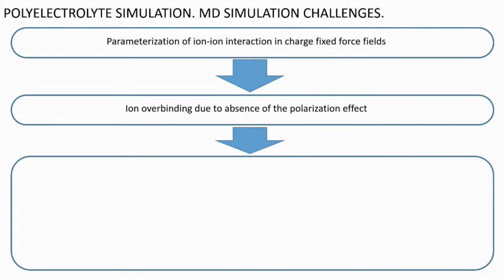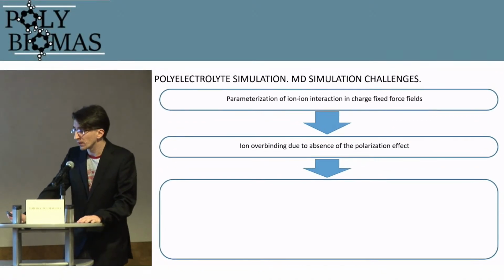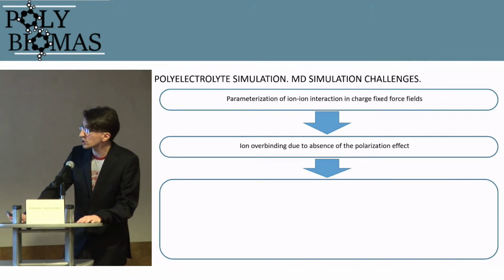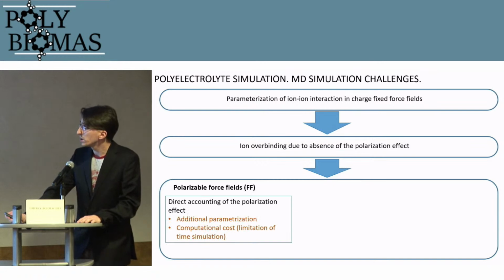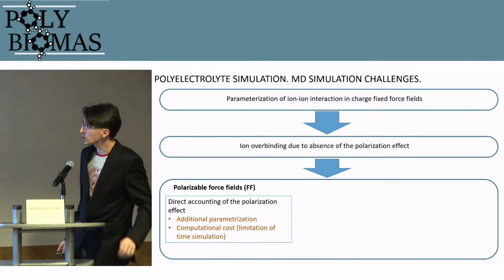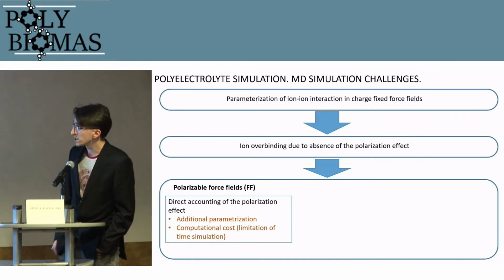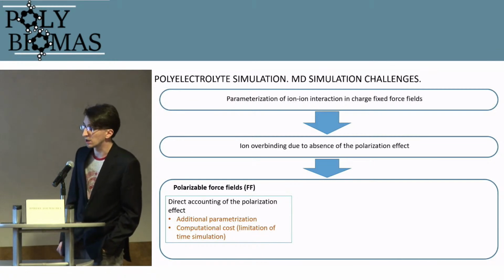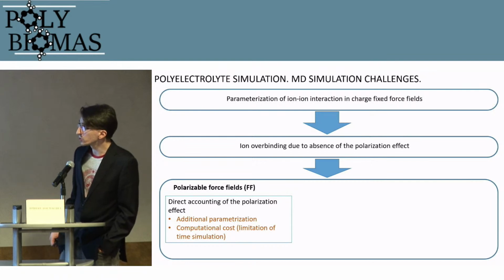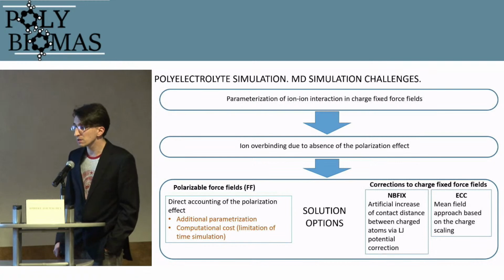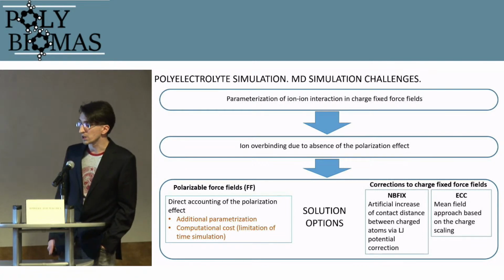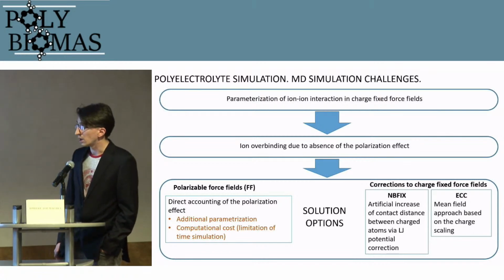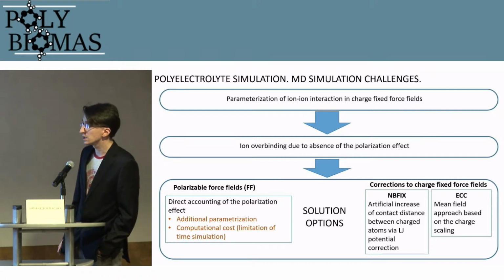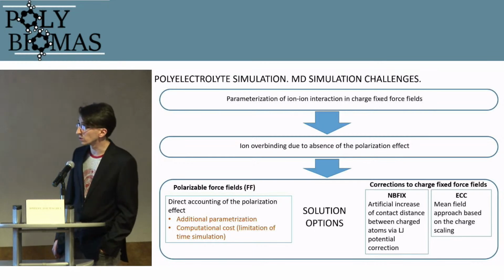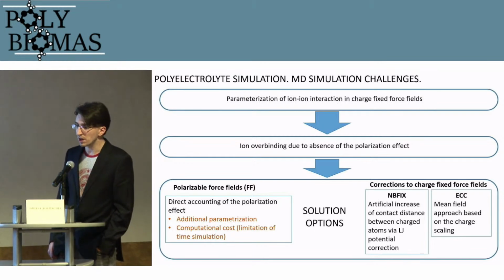And when we talk about molecular dynamics simulation of polyelectrolytes, it is important to know the challenges that we face. The first challenge was well described by Gekter yesterday, but I want to talk about it a little bit more. The parameterization of ion-ion interaction in charge-fixed force fields, and the absence of polarization effects, causes ion overbinding on polyelectrolyte. To solve this problem, one can use, of course, polarizable force fields with direct account of polarization effect, but it has a very high computational cost, and this high computational cost gives some limits to available simulation time, which of course in some cases is very important.